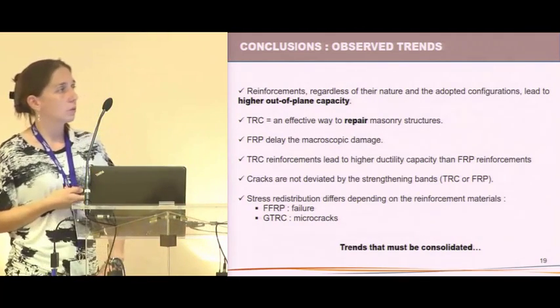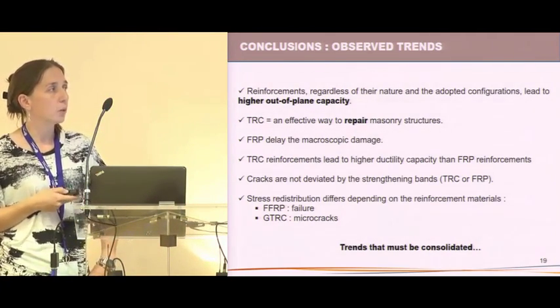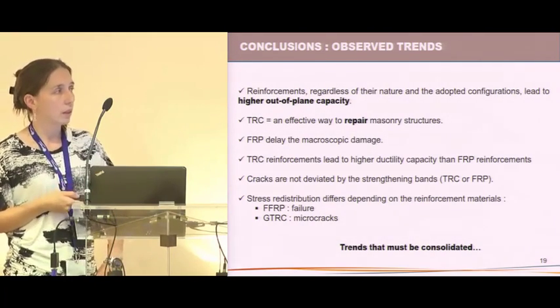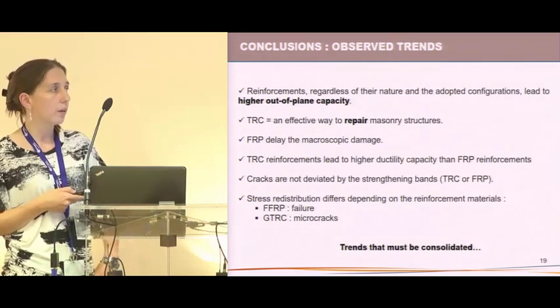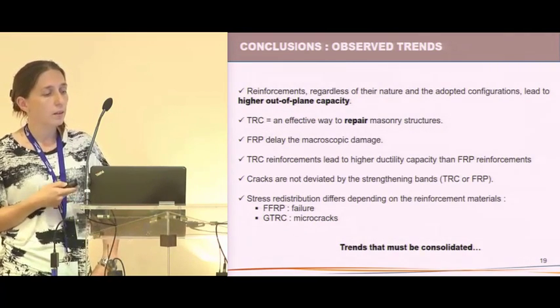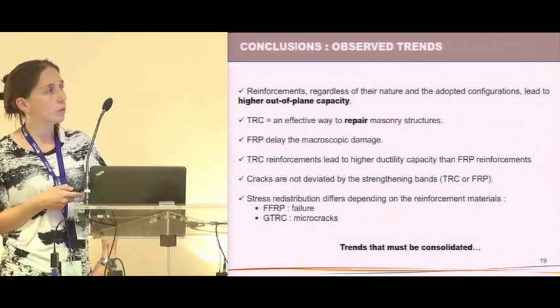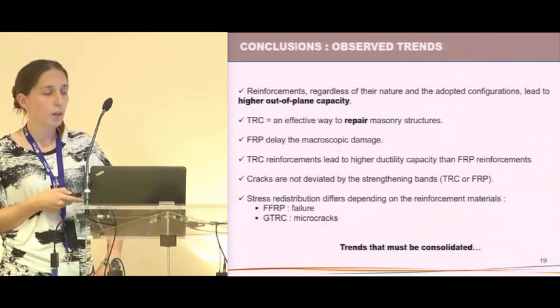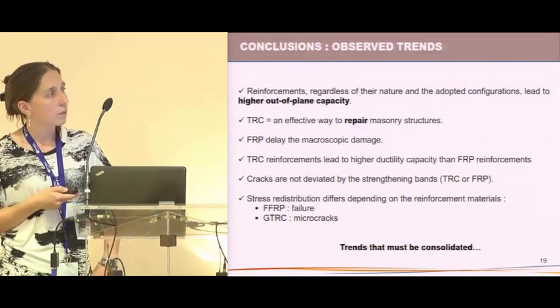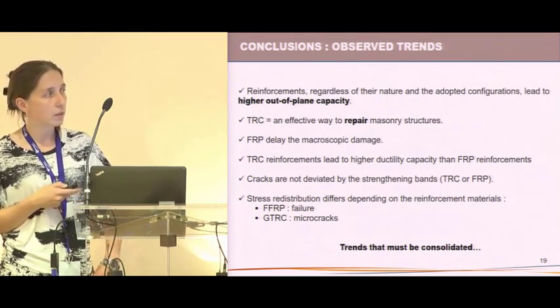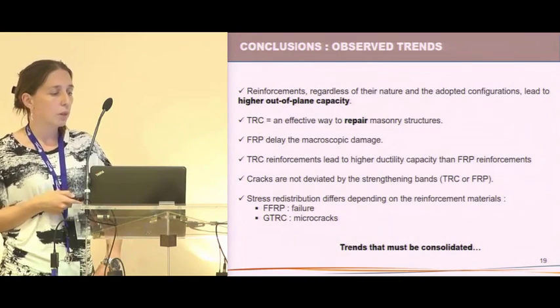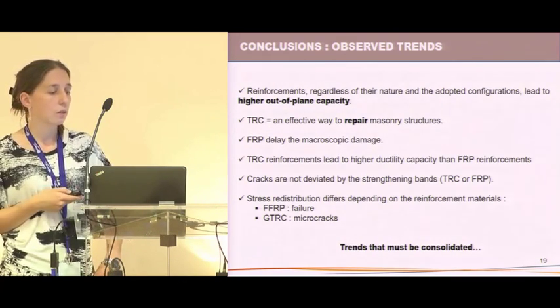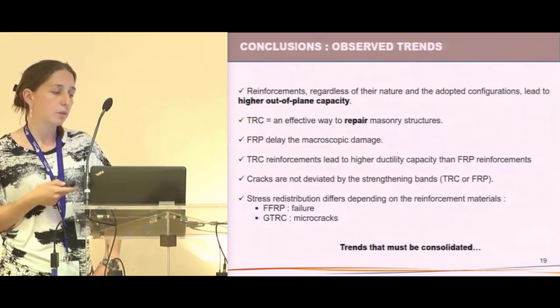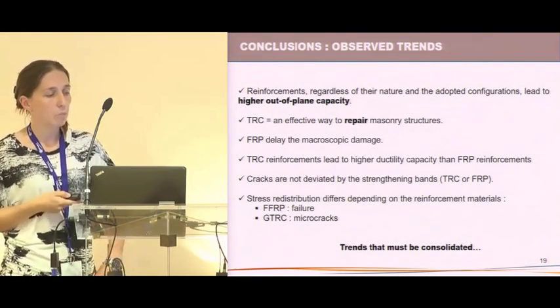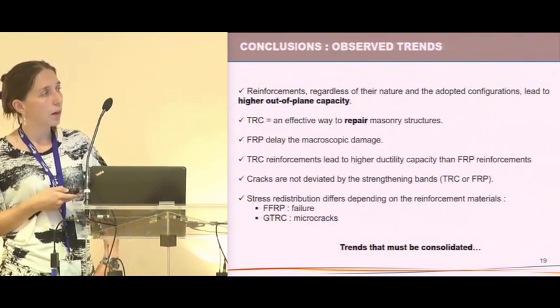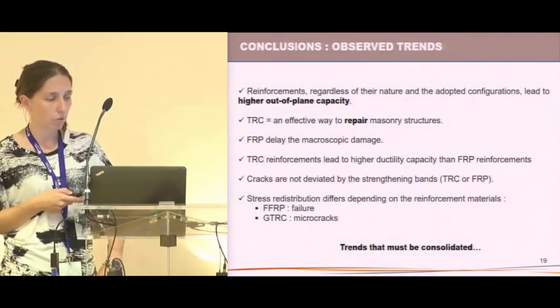To conclude, we have shown that the reinforcements that we have used, regardless of the nature and the adopted configuration, lead to higher out-of-plane capacity. We have shown that TRC is an effective way to strengthen masonry, but also to repair masonry structures. With TRC and FRP we have the same maximum load, but FRP delays the macroscopic damage. We have an advantage with TRC in our case because TRC reinforcements lead to higher ductility than FRP reinforcements.